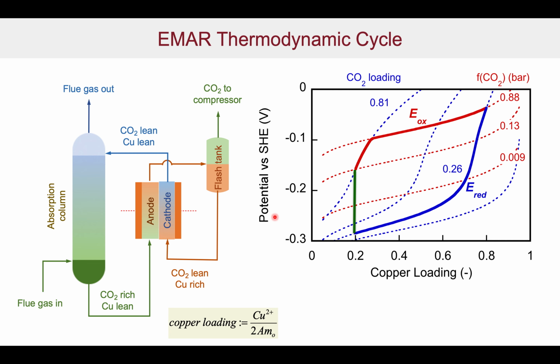This is the potential that one would have at equilibrium conditions as a function of copper loading. In other words, how much current has passed through the system, how many charges have been transported. So copper loading is really a measure of the state of charge of the system. And what we've got, the blue lines are constant CO2 loading. In other words, all the speciation of CO2: carbonates, bicarbonates, and dissolved CO2.